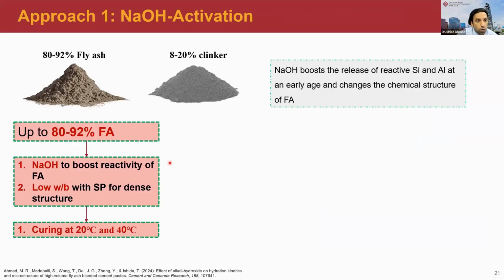In this case, we utilized 80 to 92% fly ash and only 8 to 20% clinker. So we developed the binder. To make this work, we used sodium hydroxide to boost the reactivity of fly ash, and we maintained a very low water to binder ratio by adjusting the superplasticizer. The main aim was to create a denser structure.